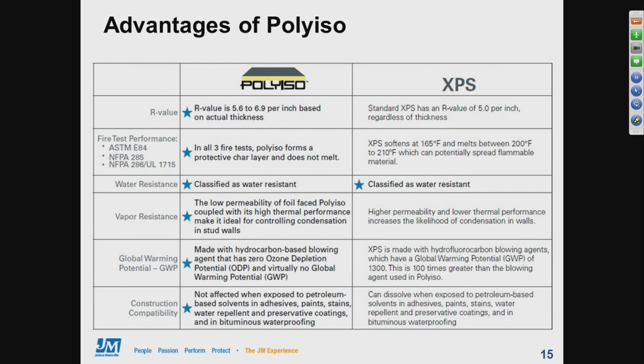Using a lower R value CI results in overall a thicker wall system, which can impact fasteners, cladding attachments, fastenings, windows and doors, and angle supports. Fire resistance is another key distinction. In a fire situation, polyiso foam forms a char layer but remains solid, whereas polystyrenes can soften and melt and even potentially drip burning liquids.